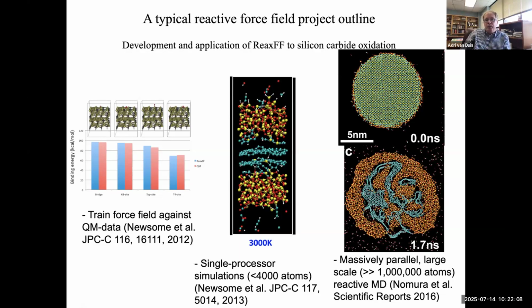And then we can scale things up. This is once again a simulation from the University of Southern California group, who very much spearheaded very large-scale MD simulations. This is roughly 4 million atoms, where we have a spherical silicon carbide particle exposed to an oxidant, in this case oxygen. After about 1.7 nanoseconds, in this cross-cut through the silicon carbide particle, we see this beautiful graphitic type of material emerging, surrounded by an amorphous silica that protects the graphitic material from further oxidation.